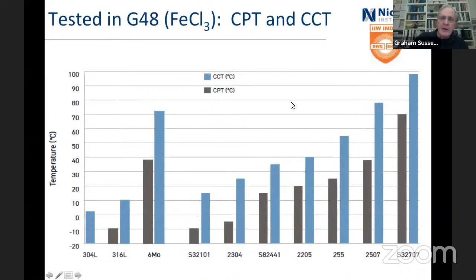That's looking at PRE. This is looking at a bundle of different alloys, austenitics and then duplexes, for critical pitting temperature and critical crevice temperature, and it's done in a test solution, in ferric chloride solution, G48. And as you can see, as you might expect, they're labelled wrong. This is an embarrassing moment because this has been used. Okay, let's just look at the fact that the whole range is steadily increasing as you go up in levels of chromium and moly and nitrogen and the corrosion resistance. And there's differences between the CPT and the CCT.